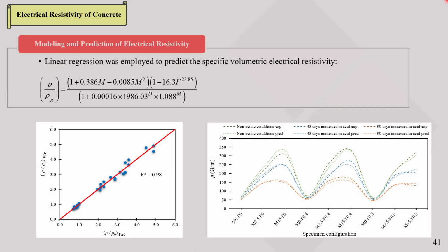The predictive model showed good agreement with the experimental results, and response surface diagrams were provided for 0-day, 45-day, and 90-day conditions. The reference sample is the one without any additives.